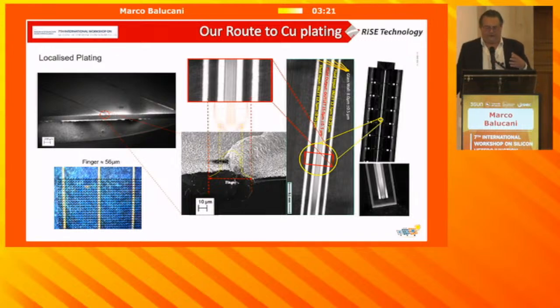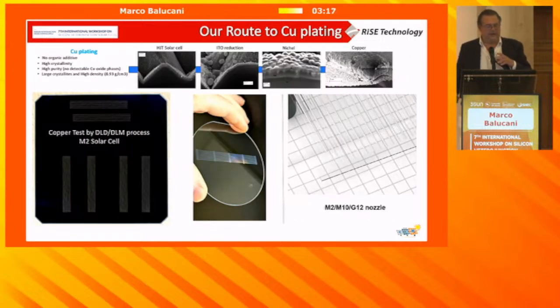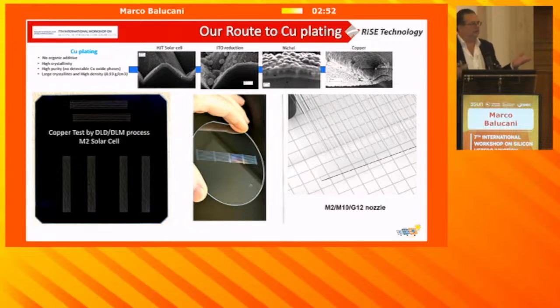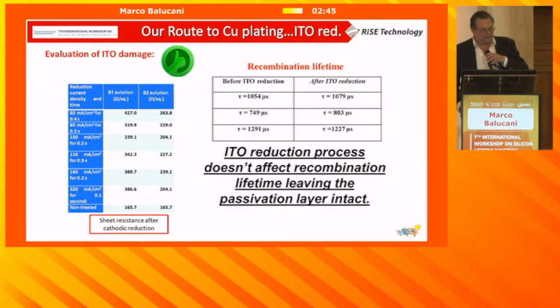So the shape then depends even on the current density and so on, but for heterojunction, the steps that we do: we do an ITO reduction, then we cover with nickel, and then we deposit copper. Here you see, for example, we are testing micron holes that we realized, and then we touch the silicon only where we want. And this is the philosophy of the equipment: you change the mask, like in stencil printing, the nozzle that you need. You need to build M10, G12, or whatever you want. You change that mask and you can do the plating you want. So what we measured is, do we damage the silicon when we do the reduction of ITO? We measured lifetime, and we don't have any kind of impact on the passivation layer.